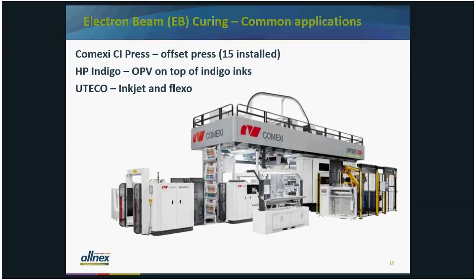And in the flexo area, a lot of E-beam flexo inks again have improved. This is with the flexo press, the E-beam is at the end of the press, and as you know, you have several colors to go through, so it's a wet on wet kind of process, which can produce some issues if you don't know what you're doing with the inks. But recently, people have overcome those issues. There's several now really interesting technologies that allow you to do wet on wet printing without getting the muddled effect from mixing the wet inks. And that's worked out pretty well.